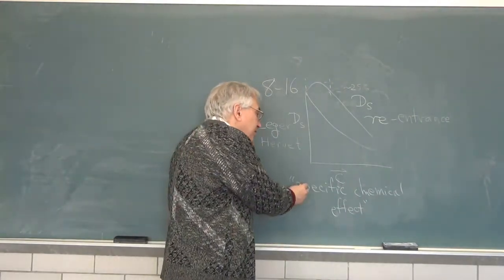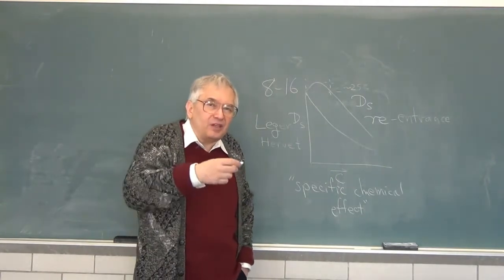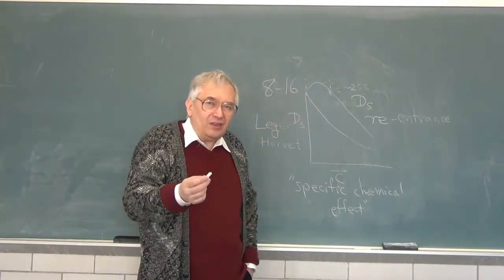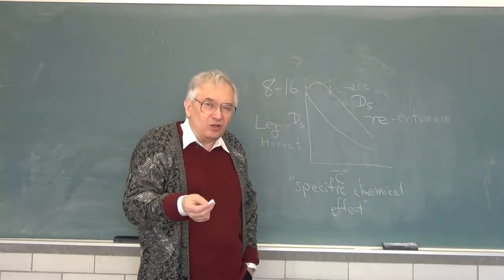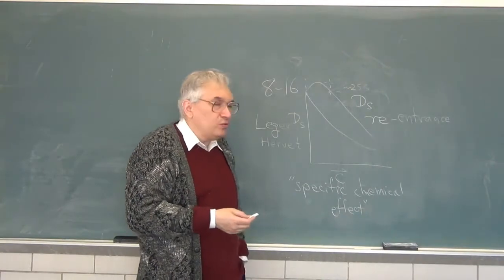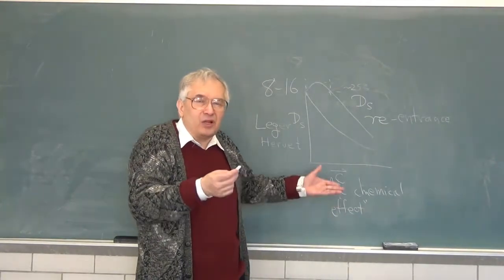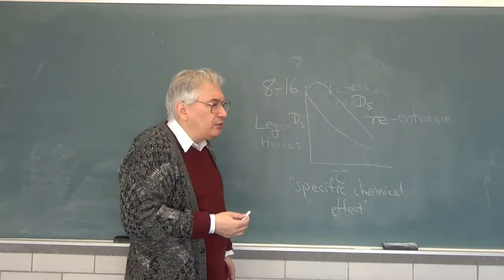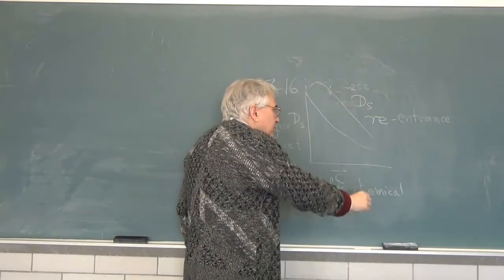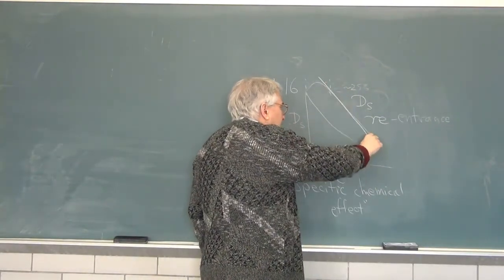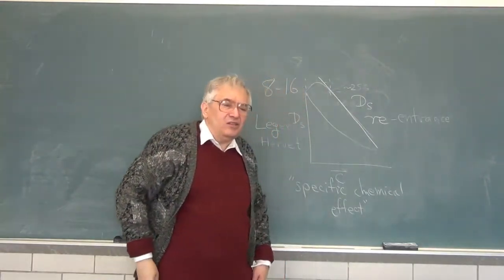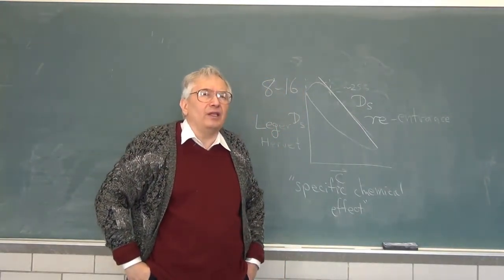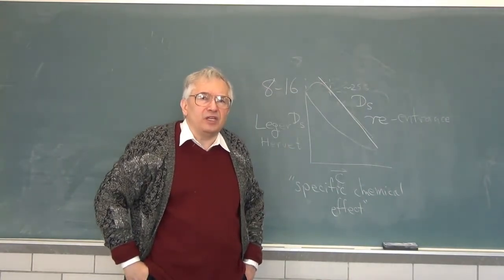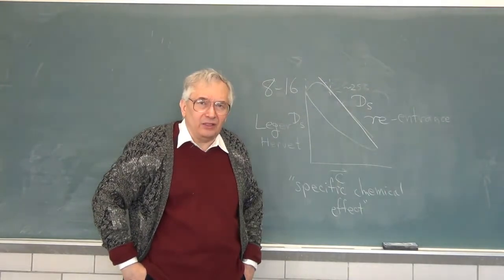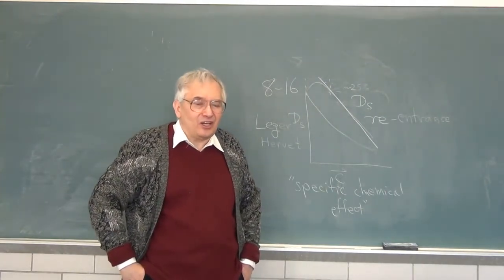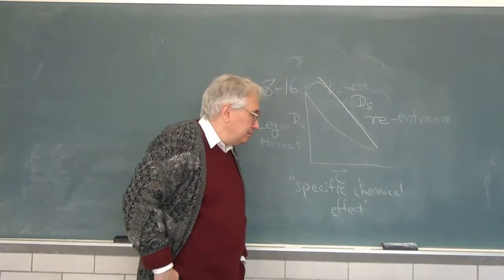However, the other point of specific chemical effect is that you are seeing something that is not the generic behavior of polymer systems, and therefore you have to sort out which measurements you look at, the bulk of them, and which measurements you decide something exotic happened, which is not the fault of the experimenters, of course. It should be noted, however, that one of the consequences of this specific chemical effect is that you appear to see scaling law behavior, and these are more or less the only measurements, they're not quite the only measurements, but they're pretty close, in which you actually can lay down a ruler on the log-log plot and say, look, clear scaling law behavior, not stretched exponentials at all. Okay.